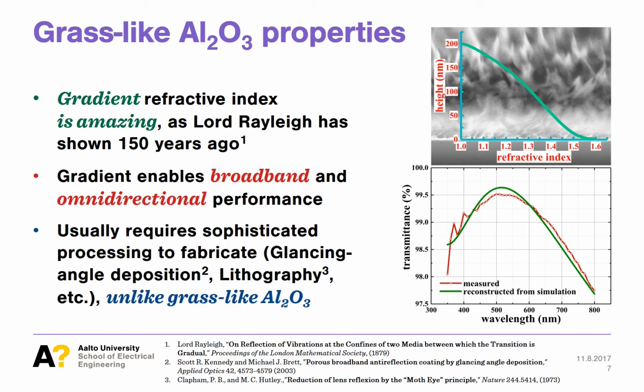It is clear from the film structure that there is a refractive index gradient, as there is more alumina at the bottom and more air at the top. It is very beneficial to know the gradient, but direct measurements are very challenging. We have used a simple transfer matrix method to fit the refractive index profile to the measured transmittance. As you can see, we have a good fit, and the obtained index profile is physically reasonable, as it approaches the value of 1.6 at the bottom, while the ALD-grown aluminum oxide has a refractive index of 1.64. This also correlates with the fact that ALD-grown aluminum oxide has good adhesion to various glass types as well as to most polymer substrates.